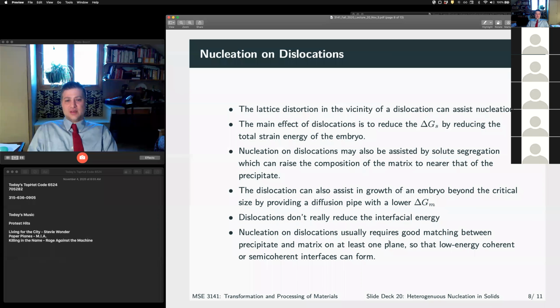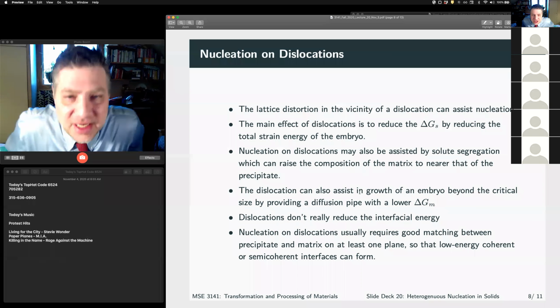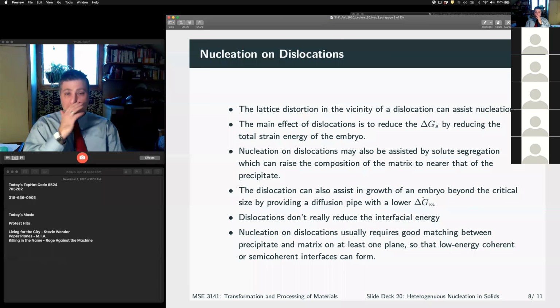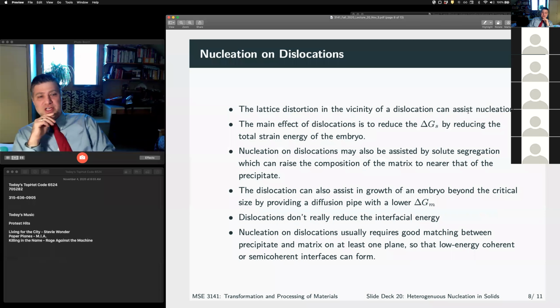right? Okay, so what about nucleation on dislocation? Well, the lattice distortion in the vicinity of a dislocation can assist nucleation, right? Around a dislocation, there's a large strain field. So if we have a delta G_S that's compatible, right? If our volumetric strain is such that by nucleating at the dislocation, we reduce that strain energy, it's going to give us a boost.